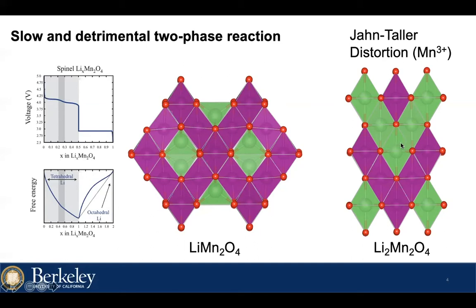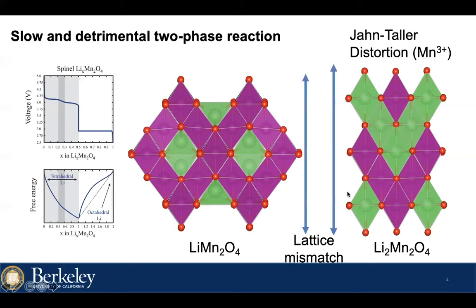And the well-ordered structure will make the Jahn-Teller behavior collective and elongate the c-axis. The mismatch in the c-axis between these two phases creates a large strain at the phase boundary, and this will move through the particle during the cycling. After a few cycles, the particle will crack and finally fail. So lithium manganese spinel can never practically cycle in the 3 volts region due to this problem.